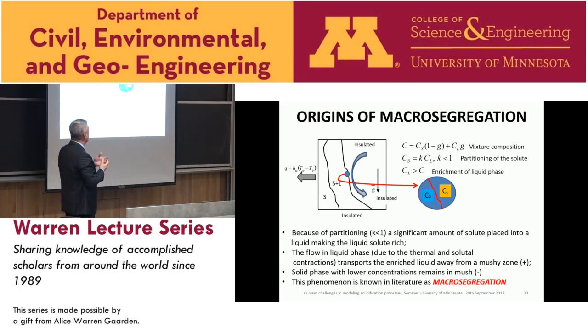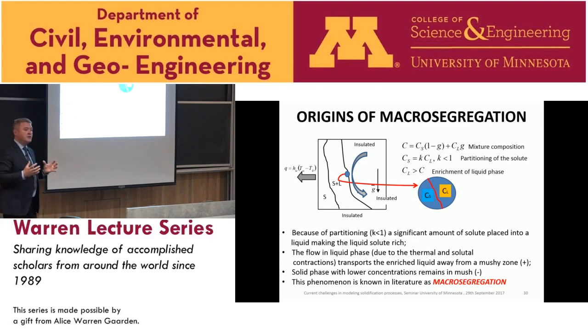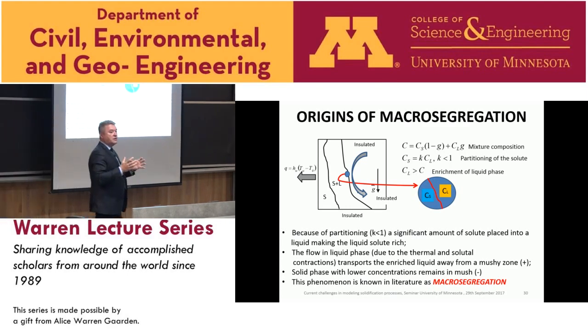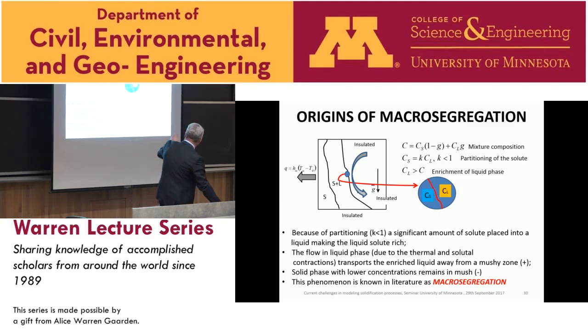Because of that, the liquid becomes enriched. And this enriched liquid is advected by the flow to some place in the casting. And then you have a decomposition. You have zones with positive segregation and zones with negative segregation. This is a very undesirable effect in the metal industry. In the metal industry, they want everything to be as uniform as possible, and they are not interested in such a phenomenon. We call it macro-segregation.